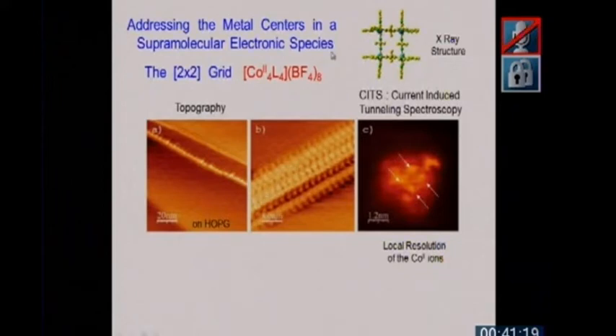Now, what I said up to now deals with properties in the bulk solution. What about now looking at an organized entity, that means depositing these units on a surface, so you can perhaps talk to them. If you take, this is now the cobalt grid, you can deposit this cobalt grid on a graphite surface, and here you see rather regular, nice arrangements. And if you look more carefully, this is the image obtained by scanning tunneling microscopy, where you see 4 dots, 1, 2, 3, 4, which correspond exactly to the 4 cations in the structure.